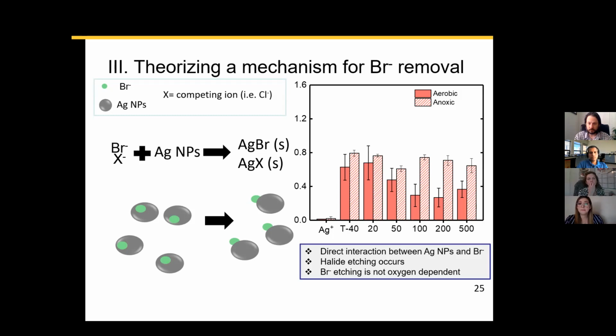Another thing that we found is that bromide etching is not necessarily oxygen dependent, and that's why most of our materials have a similar bromide removal capacity. When we compare that to chloride, we actually see less removal capacity with chloride ions present.